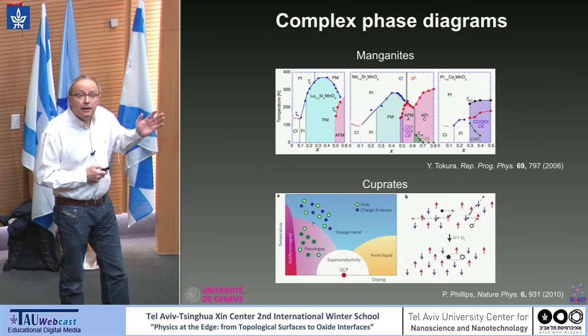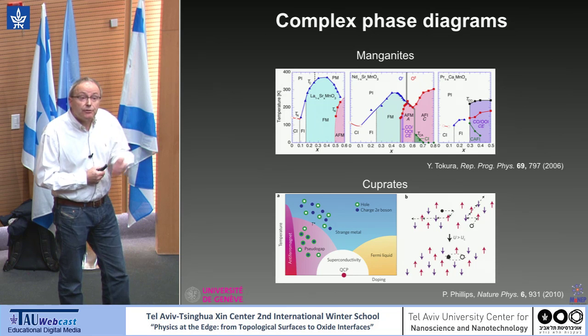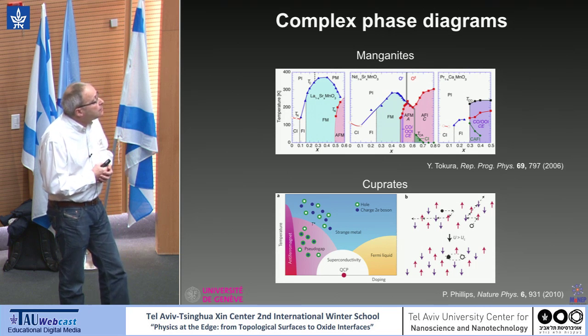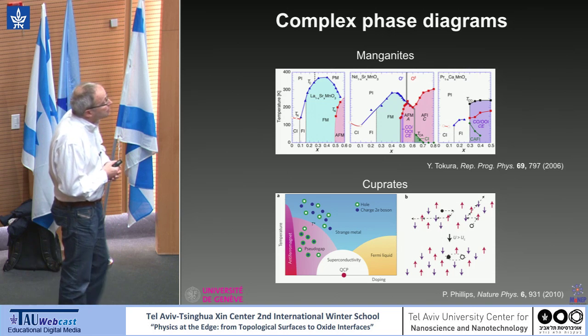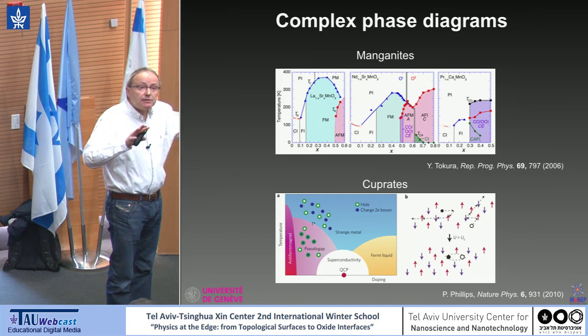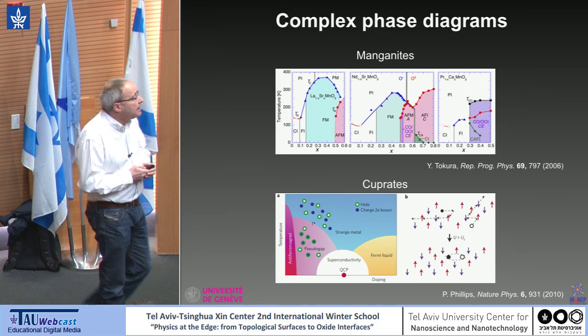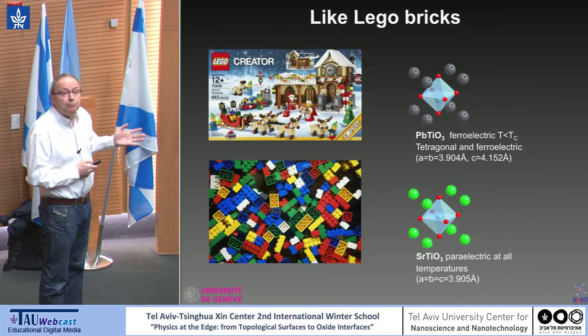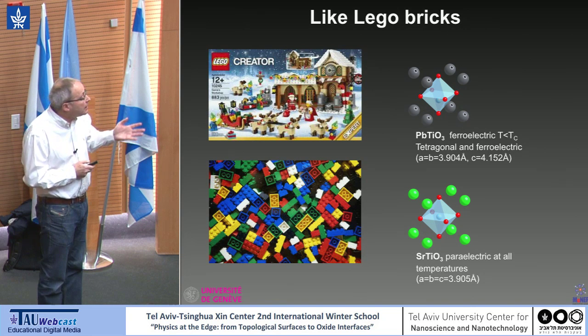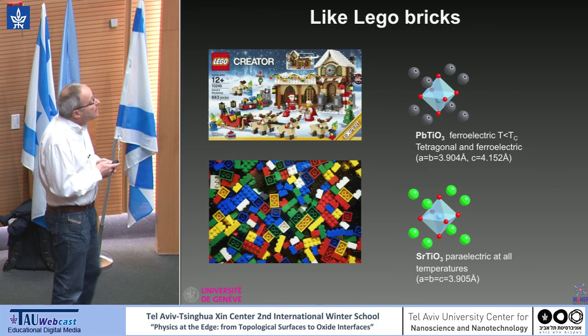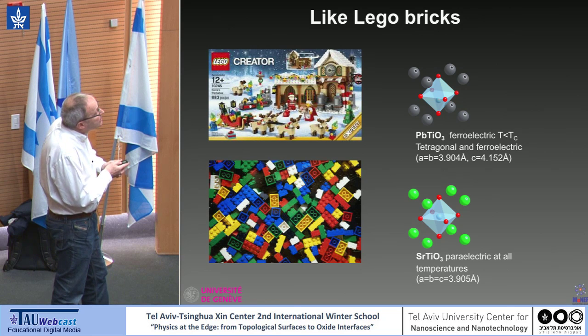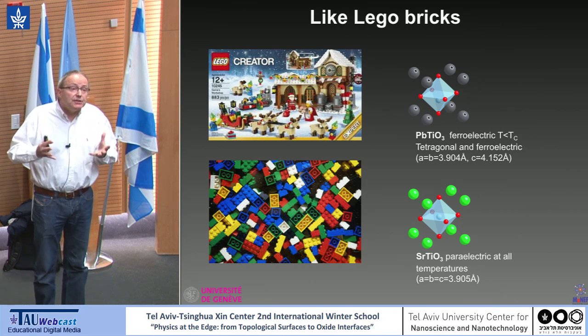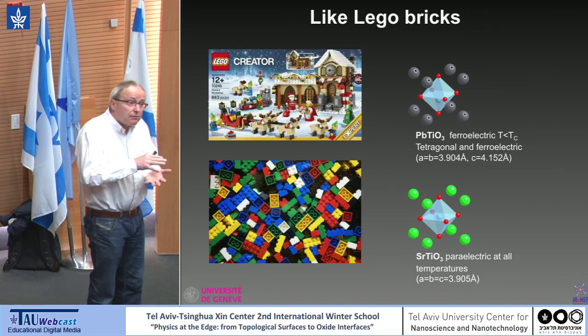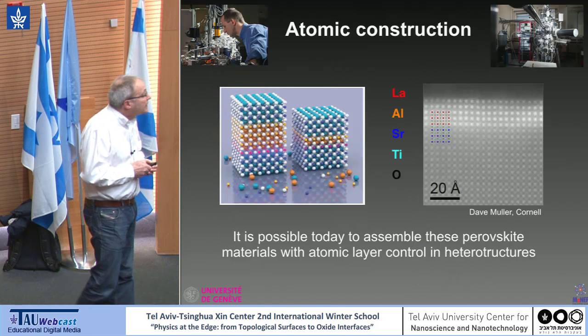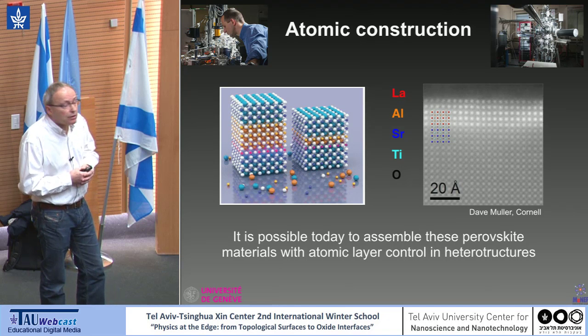This is also why one believes that these materials are probably very good materials for sensors, because eventually a small stimulus can lead to a large response. Now, I just said that these materials belong to the same family. And so it's a little bit like Lego bricks that one can pile up very precisely. You see here examples of lead titanate and strontium titanate, and you see that the lattice parameters are also very similar. So today we have different techniques which allow epitaxial growth of these compounds, and beautiful and very perfect structures to be realized.